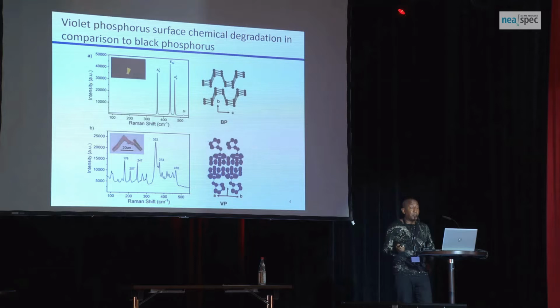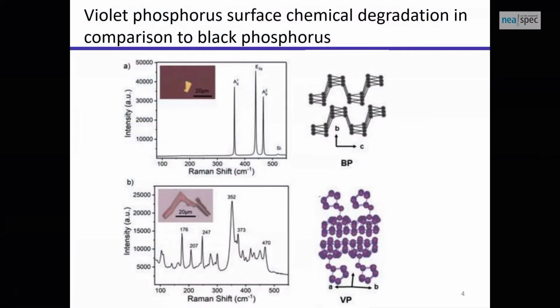So then you do something about it, and that is you passivate it. My group and others have worked on this, and what we found is that if you have a double layer coating, you can passivate it for quite a while. Recently, instead of working with this one material that is quite reactive, we started looking for a newer allotrope of phosphorus, and we have found that violet phosphorus, the other allotrope of phosphorus, is quite stable, much more stable. Of course, when you work with phosphorus, that's the first thing you ask: is it stable? That's the important question. We did the first experiment on this material, and we found that, depending on what substrate you use, it can be actually quite stable without having to coat it, at least for a while.